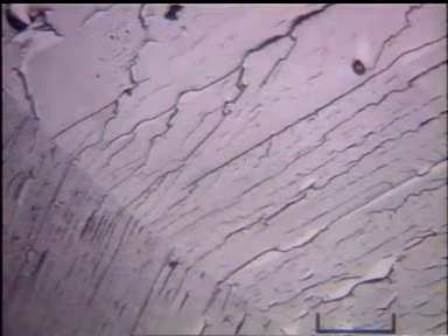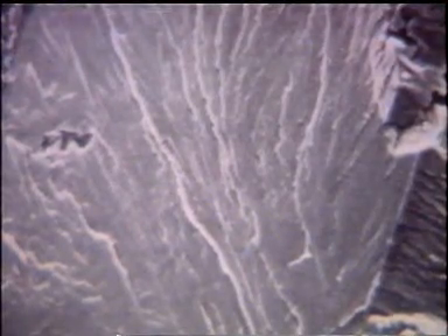The cleavage fracture frequently initiates on many parallel cleavage planes. As the cleavage fracture advances, the number of active planes tends to decrease by a joining process. The planes join to form higher cleavage steps. This network of cleavage steps is known as a river pattern. Because the branches of the river pattern join in the direction of crack propagation, the marking can be used to establish the local direction of the fracture. Feather markings are a fan-shaped array of very fine cleavage steps on a larger cleavage facet. The apex of the fan points back to the fracture origin. Tongues are occasionally observed on cleavage fractures. They are formed when a cleavage fracture deviates from the cleavage plane and propagates a short distance along a twin orientation.